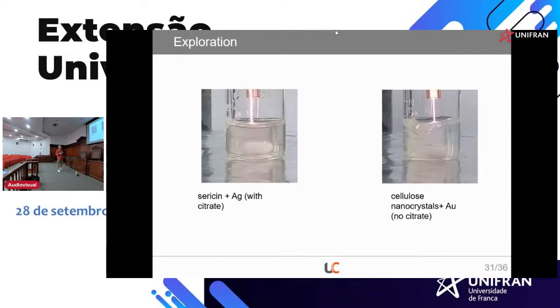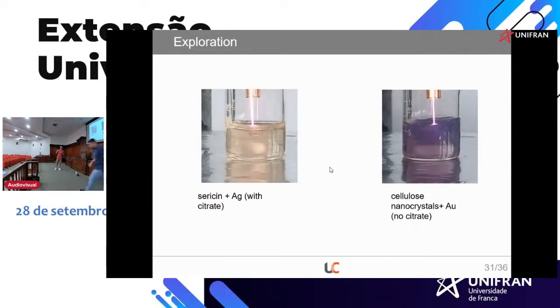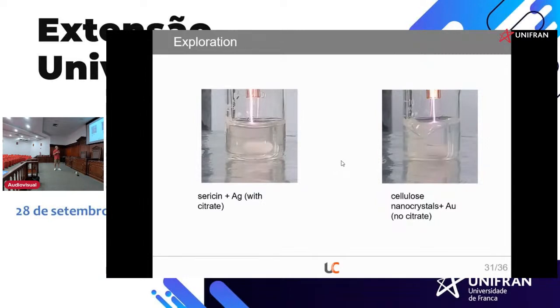Here there are two videos. We made this solution yesterday because it's quite well known to produce particles, but we try to produce them directly in cellulose. So we can have some film with nanoparticles directly inside. Here it was gold and the other one was silver.